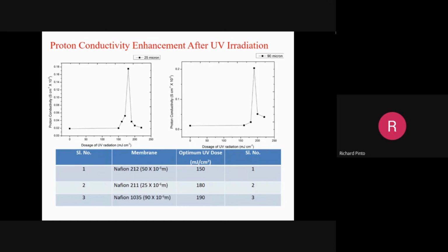Actually, there is a mistake here. This is 20 micron, 50 micron is 25 micron. This should be interchanged. So the dosage increases with the thickness increasing. There's a mistake here. Okay, I didn't check the slide. So 25 micron, this is 211, this is 212, 50 micron. And then dose increases, 150 millijoules per centimeter square, 180 millijoules and 190. So 196 was obtained in the earlier case. It's more or less the same. So slight experimental variation is there.